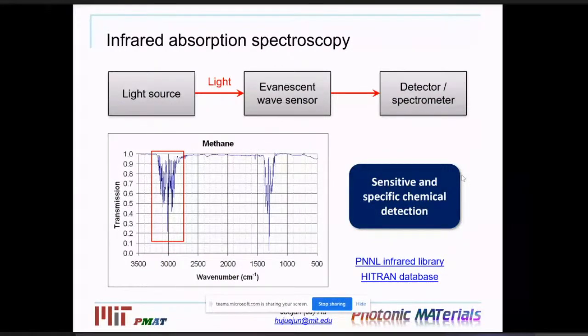Now, how does this photonic sensor work? The principle we're using here is so-called infrared absorption spectroscopy. We have some kind of light source. We then pass it through a device in the form of an optical waveguide. And in this waveguide, the light can actually interact with the molecule through a so-called evanescent wave. Essentially, the light field that spills out of the waveguide core can directly overlap with the molecules in the ambient environment. And then when this interaction takes place, the molecules selectively absorb light at some selected wavelengths. So then finally, the optical spectrum as a function of wavelength is detected using a detector or spectrometer.